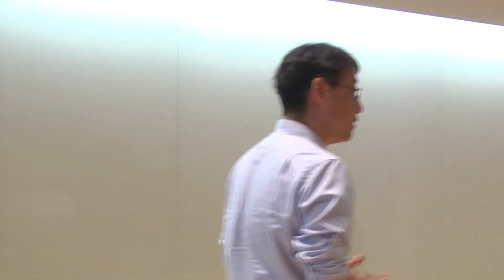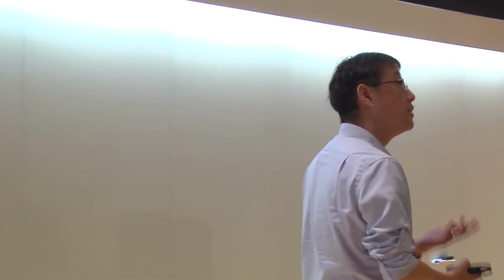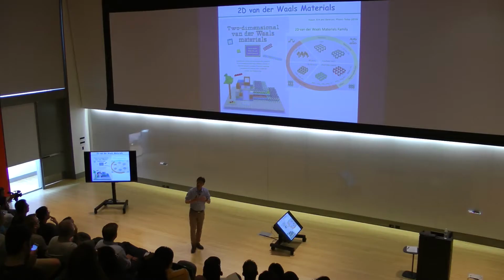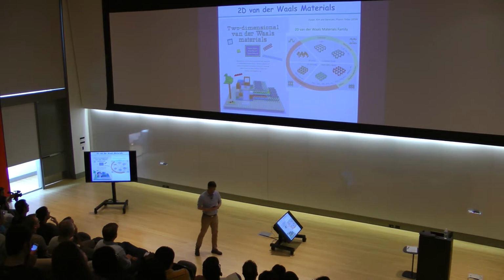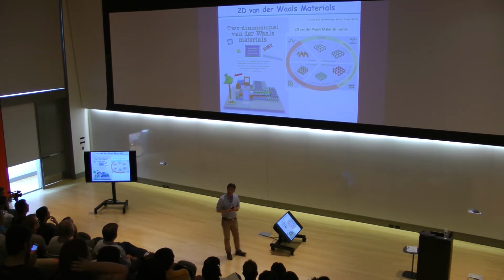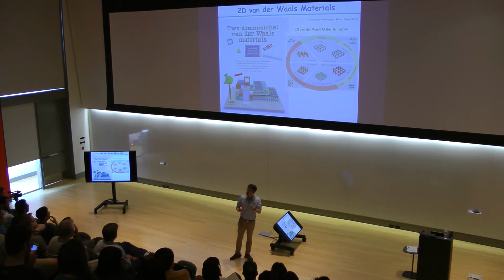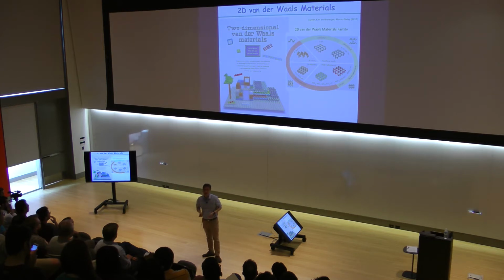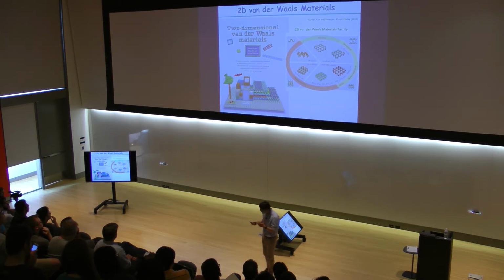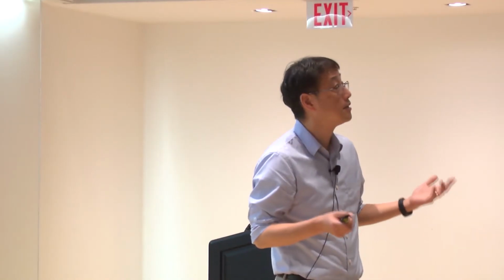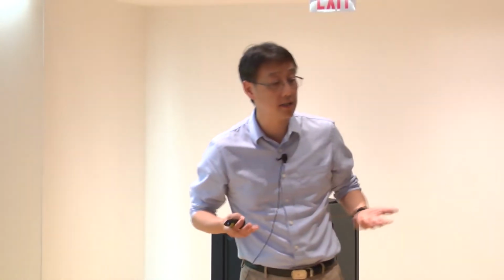In this material, the chemical bond is within the atomic layer. But between the layers, there is no real chemical bonding. It's just weak van der Waals forces holding them together. Because of this weak van der Waals force, the first thing you can realize is that many of these materials can be simply cleaved quite well using Scotch tape. About 12 years ago, people demonstrated you can break the graphite down to a single atomic layer of graphite, what we call graphene. That is possible simply because the material is stable, because all the chemical bonds are within the layer.